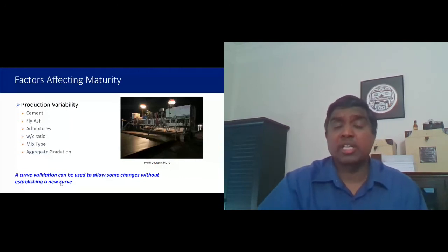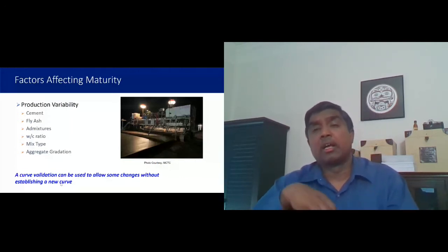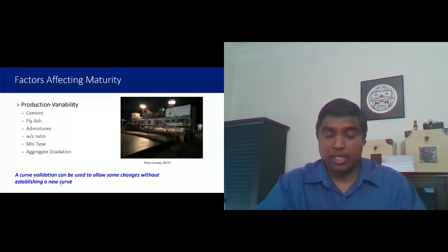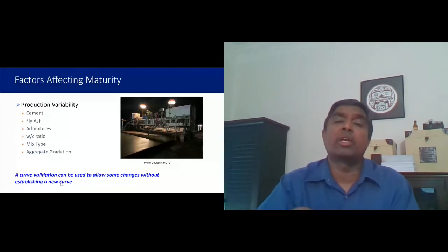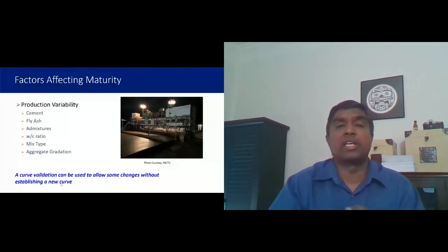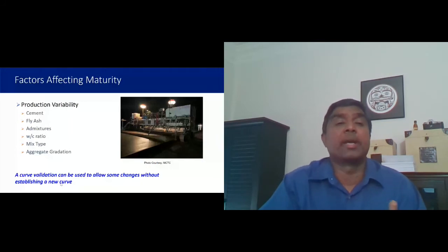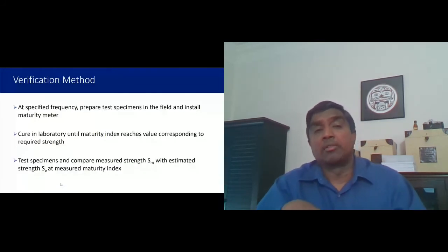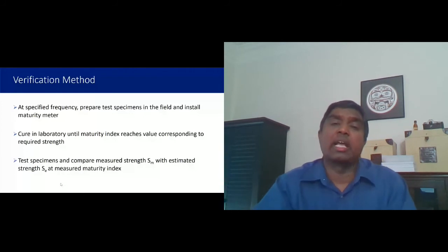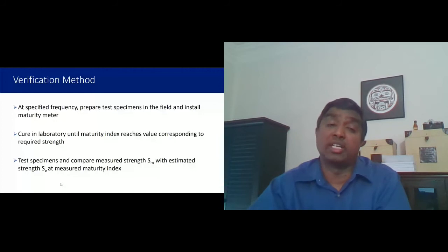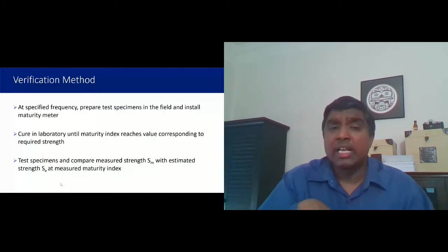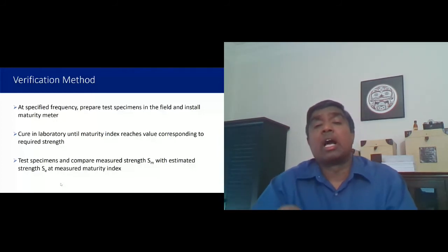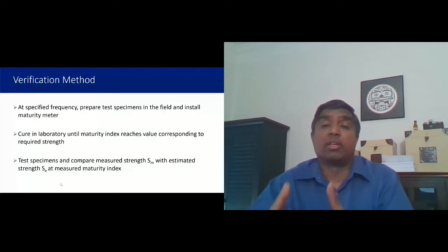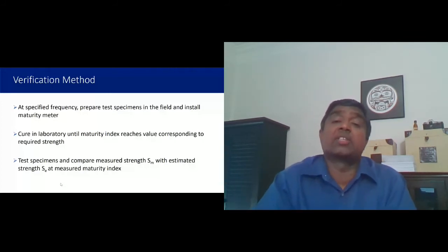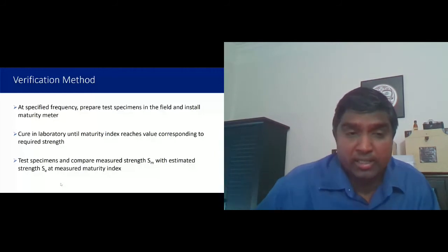Now, in some states that do specify the maturity test method, they do require that the calibration curve is verified periodically. So basically what they do is they specify a frequency, and then test specimens are prepared in the field and a maturity meter is installed in them. And then these specimens are cured in the lab until the maturity index, which is the maturity number, reaches a value corresponding to the required strength.